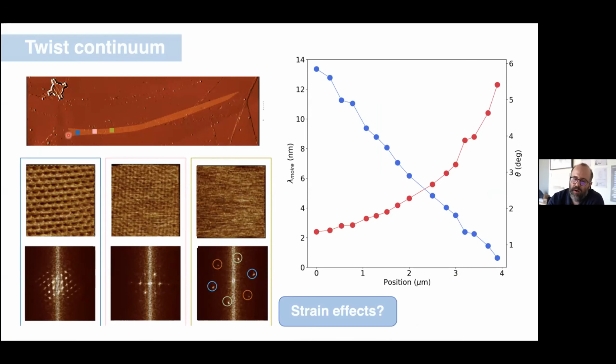The strain is maximal at the tip here, so we can measure as a function of increasing strain down this bent noodle by making side-by-side Hall bars. There's some evidence that in that situation, a gap is emerging, whose origin we don't really understand in the case of graphene on BN. We actually bend it away from BN alignment and we see that a gap emerges.